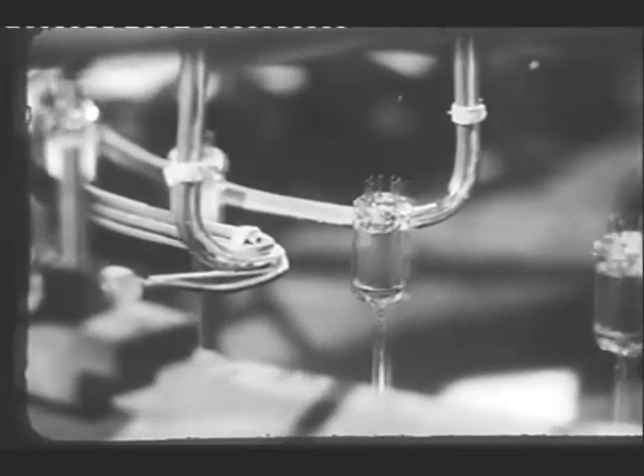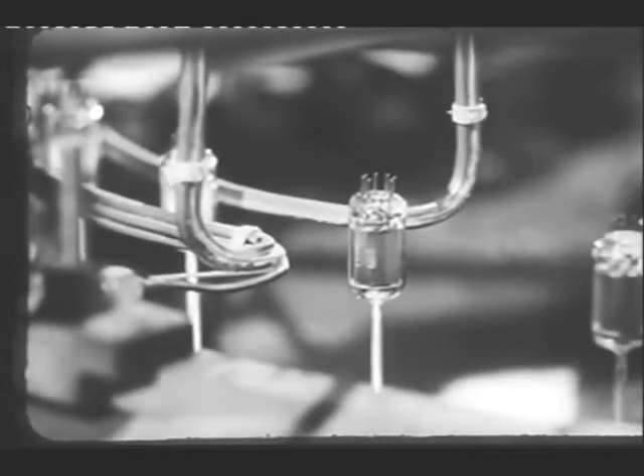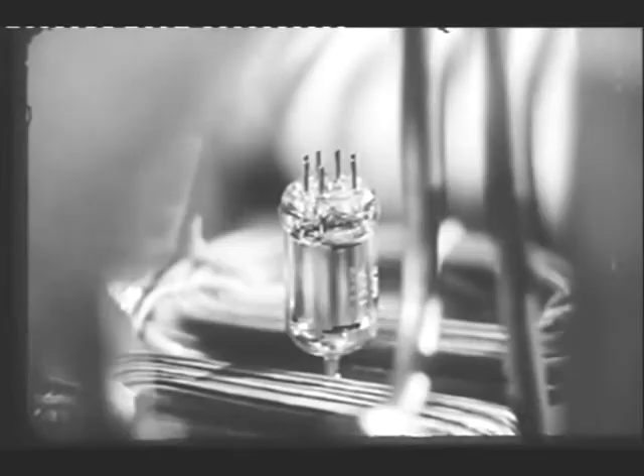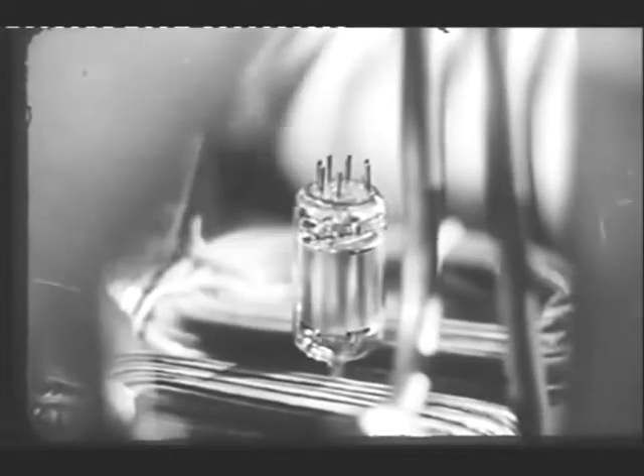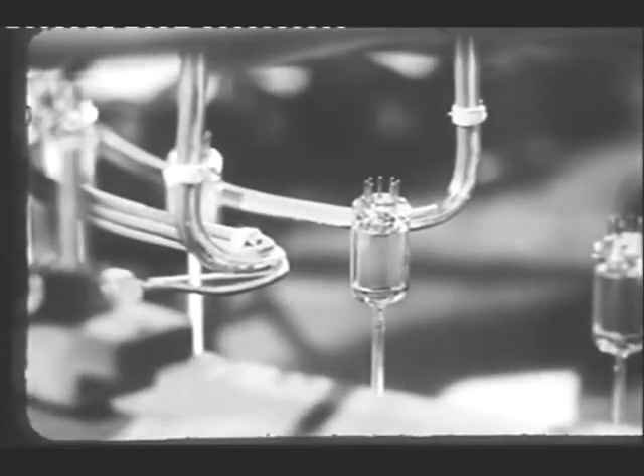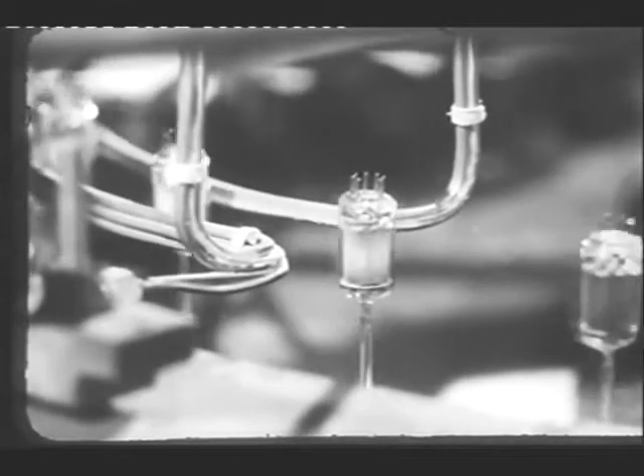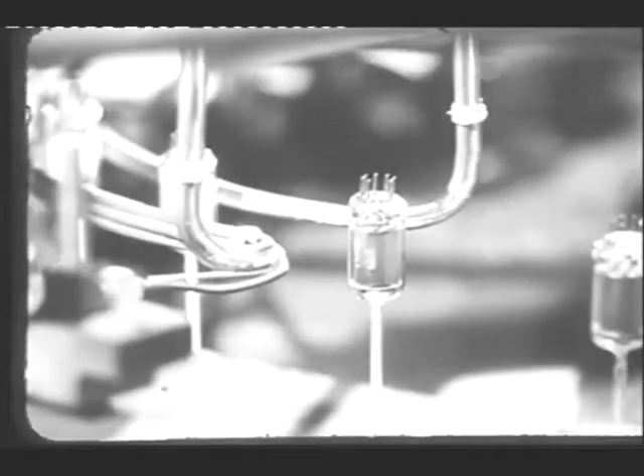Then through coils carrying high-frequency currents which heat the metal parts and drive off more gas. A current through the heater heats the cathode and so reduces the coating on the cathode to oxide, thus forming the emissive surface. High-frequency currents also evaporate the getter to absorb the last traces of gas.